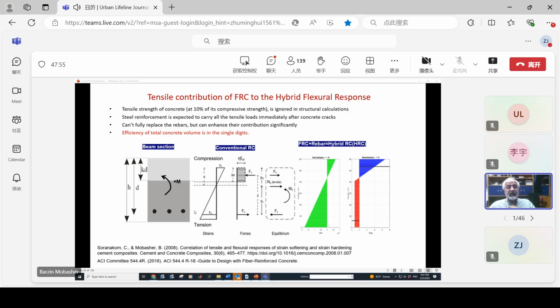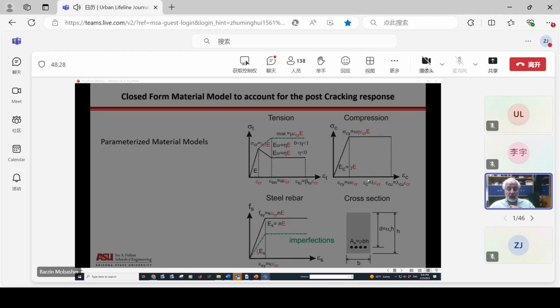And this is the approach that we chose to actually simulate this, except one thing, and that is we don't use this stress block. We don't go from strains to forces. We use the compatibility condition to generate the stress distribution. And if we do that, we find out that the difference between the strain distribution should translate into a stress distribution if I need to take into account the tensile capacity of the concrete. And that's how it would look. So the question is, how can I get these solutions in closed form?